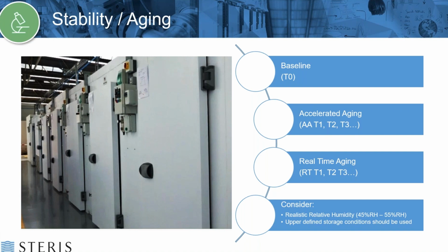And then if you have a defined storage condition, say you have to store your product between 20 and 30 C, the upper defined storage limit should be used in the calculation for your accelerated aging as the ambient condition for that calculation. So that calculation is going to use both the temperature that you're performing the accelerated aging at, as well as that ambient temperature. So if you got 20 to 30 C for storage in your product, you're going to want to use 30 C for that ambient, as opposed to like a 23 C that many people will use.